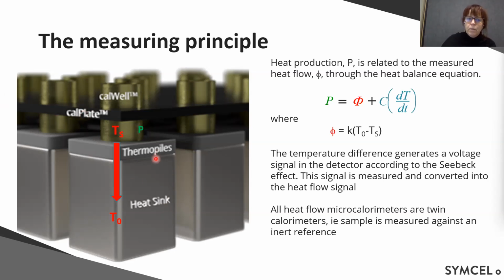Inside the calorimeter, it looks like this. You have your sample vial. It will be standing directly on what we call the thermopile. This is the heat detector. The heat detector is directly connected to a heat sink for this individual channel. We see they are separated between the channels, but this is also directly connected to a bigger heat sink. This heat sink and the whole calorimeter unit sits in a thermostat that keeps 37 degrees. And then you have air surrounding everything.